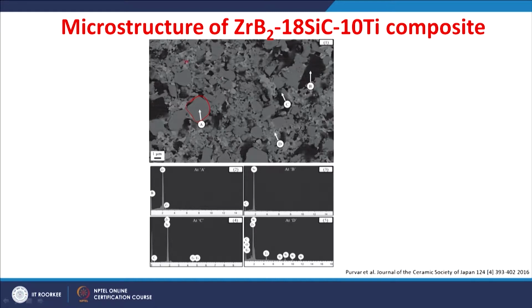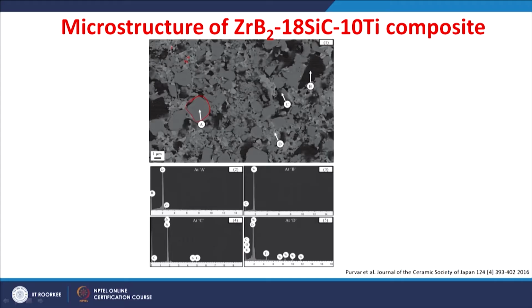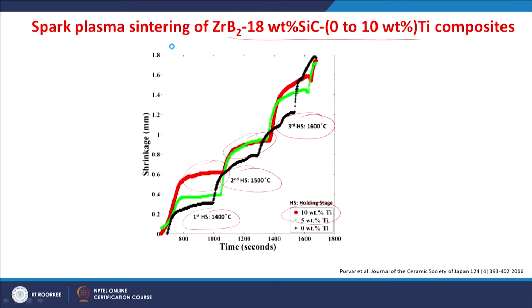right, silicon carbide particles, and then titanium. The titanium being a lower melting material, it forms a liquid melt while increasing the temperature during sintering. This liquid melt penetrates between the particles of the zirconium diboride and silicon carbide and facilitates sintering. Such a liquid phase sintering gives us a densification earlier than that used without this titanium.